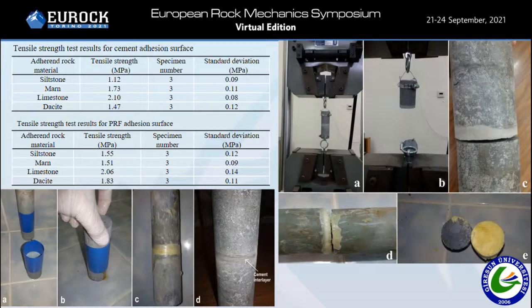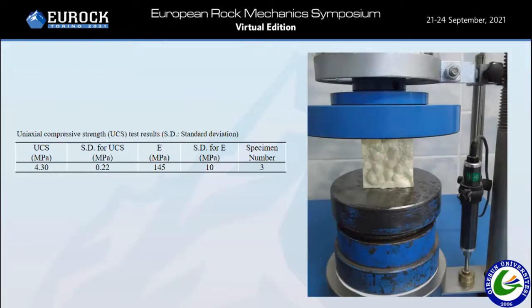As I noted before, the adhesion performance to rock contact surfaces is another important parameter for liner materials. So the adhesion tests were carried out within this study, and the results have been obtained from this test. Also, uniaxial compressive strength tests of the PRF material have been carried out within the study.